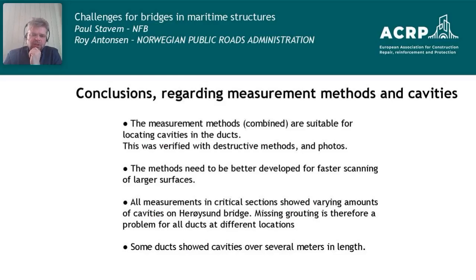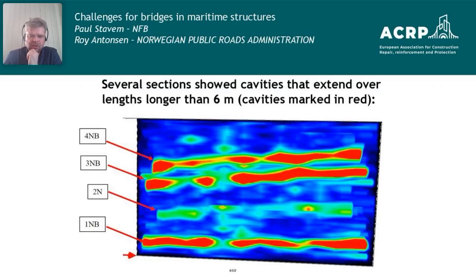The conclusion from this work is that the measurements combining ultrasound, ground penetrating radar, and impact echo together are suitable for locating cavities in the ducts. The methods need to be developed for faster scanning of larger surfaces, and all the measurements in the critical section showed varying amounts of cavities in Herøysund Bridge. Some ducts showed cavities over several meters in length, as this one. This is 6 meters in length here, and you can see that the red areas are totally voids.